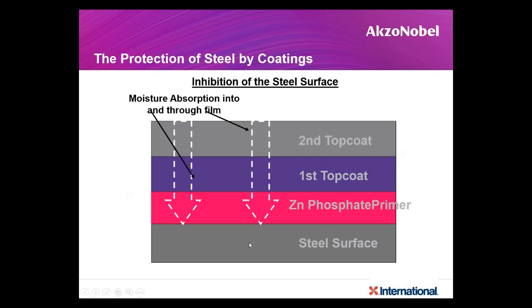Then inhibition of the surface. When you look at the steel surface, the inhibiting primer is nothing but a zinc phosphate primer. Since the coatings when applied are a little permeable, they can allow moisture to come in contact with the steel. Now, when it comes in contact with the steel, this zinc phosphate reacts with the moisture. It forms phosphoric acid. That phosphoric acid will react with the steel to form a ferrous phosphate layer, which is an inert layer. This layer will act as a barrier against further corrosion. So the second method is to use inhibition of steel by using inhibitive primers. Keep in mind, the first one is cathodic protection, the second one is corrosion protection by inhibition.